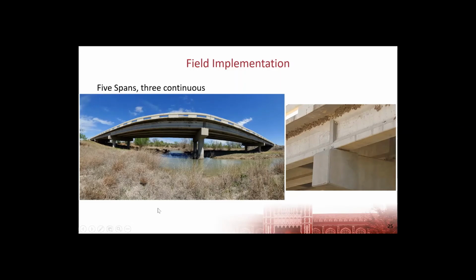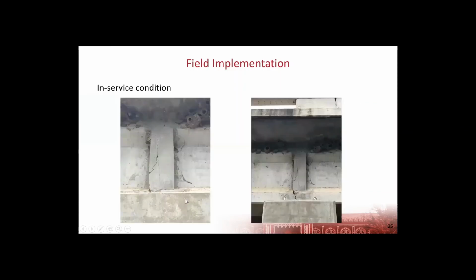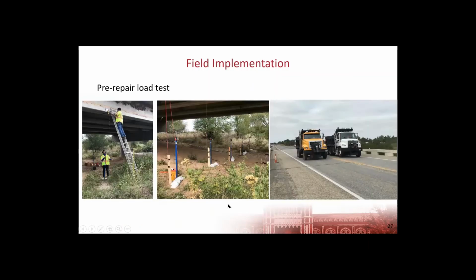And those 3 spans were connected using these individual continuity connections. Every one of them had these cracks that are indicative of the effects of restrained creep and shrinkage within the beams. And initially, we did a load test of the bridge before we repaired it to get a feel for the initial condition and the level of continuity that was present.